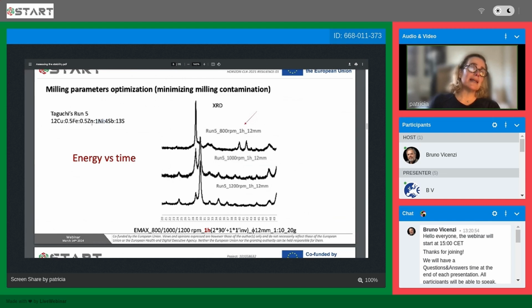currently. So the idea here was to make sure that we could get homogeneous compositions in tetrahedrite, starting from the elements, not from minerals. So here what you see is that we are trying to see what happens when we change the rotation of the ball mill. And here we're talking about energy, the impact energy provided by the balls to the material.